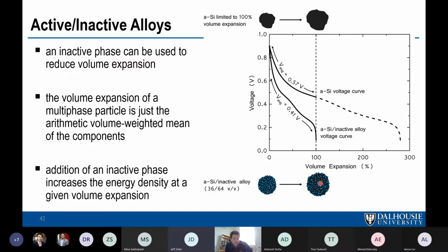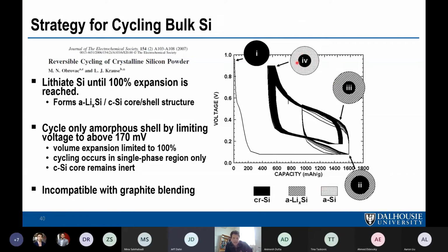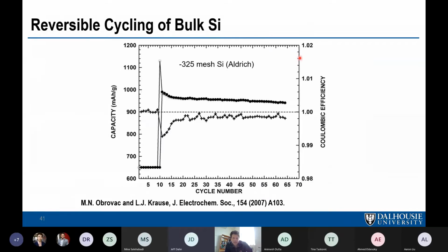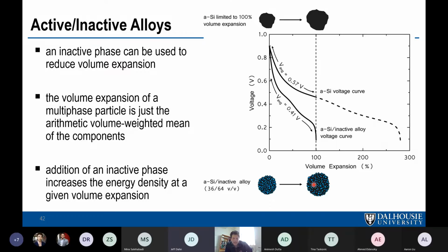But still, these inactive particles, or grains, are not expanding at all, and the silicon is expanding. So back here we had said this is kind of like that copper foil substrate with a thin film on top. Well, now you've got a lot of substrate covered with silicon, basically. So it's kind of the same idea. And there's going to be a huge amount of stress on these phase boundaries. One way to deal with that is to make them nano, and if you do that, then you don't tend to form cracks that can propagate, and these particles tend to stay together better. And you get a more homogeneous distribution of the strains, or the stresses, excuse me.